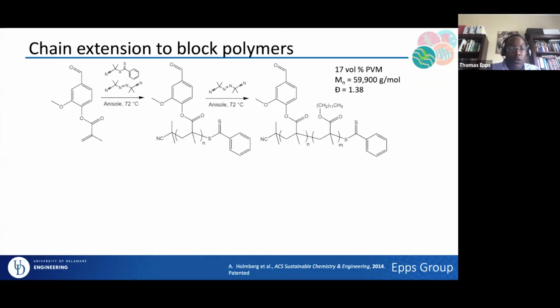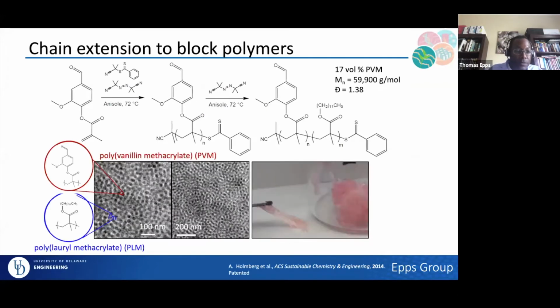But we can take that and actually polymerize it, in this case as a block copolymer with lauryl methacrylate, which we can get from used cooking oil. We actually got this from one of the dining facilities at the University of Delaware. And we can make that block copolymer, and one of the nice things about it is shown in the electron microscopy images here. We have TEM, and as you can see after staining, we have dark regions of spheres in a light matrix. That's quite nice because that's that very nice thermoplastic elastomer type structure that we would want.